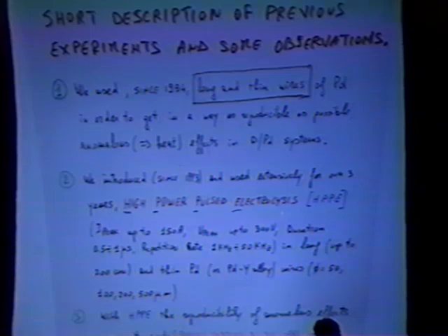And we used high power pulsed electrolysis, very fast rise time of the order of 100 nanoseconds, some proper frequency range, and with some proper duration. We used palladium alloy, and we tested several wire diameters, and we found when the wire was smaller diameter, all worked better, and the faster the system was.